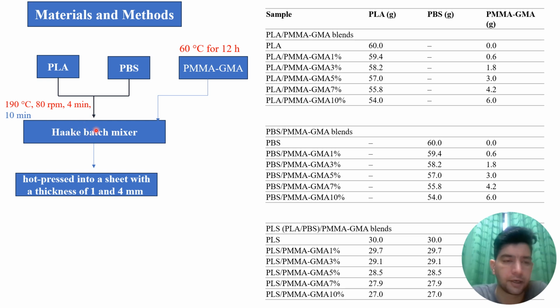After melting the blend, they introduce the PMMA-GMA compatibilizer and remelt again at 190 degrees centigrade at 80 RPM for 10 minutes, and the resulting polymer blend was received and then hot pressed into a sheet with a thickness of 1 and 4 millimeter. The polymer blends formed have different weight percentages of PLA, PBS and the compatibilizer. All data are shown in the table. They also made controls: pure PLA, pure PBS, and the blend.